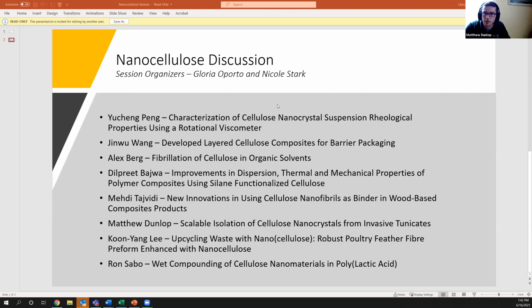The first study, we looked at polyvinyl alcohol and combined high aspect ratio tunicate CNCs and low aspect ratio wood CNCs within that polymer matrix. And we found synergistic mechanical reinforcement, specifically looking at the elastic modulus. Now it's an early study and it looked at specifically cast films. So we wanted to kind of build off that and see if we could do something a little bit more relevant to industrial practices.